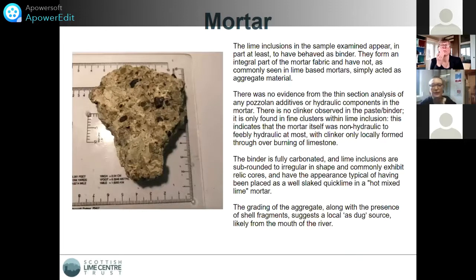And the summary we have from that is that the lime inclusions seem to be acting as a binder rather than as an aggregate. And that just means that they'd diffused with the surrounding binder. And there was no evidence of any additives. So sometimes things like ash are added to a mortar, and that's to make it have a more hydraulic set. And there was no main clinker observed apart from the stuff that was found within the lime inclusions.